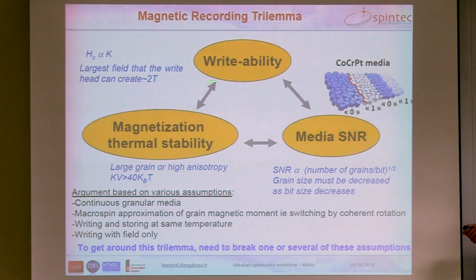But if we increase the anisotropy, now we have a problem of writability, because this electromagnet, the writer, which is a small electromagnet, can at most deliver a field of the order of 2 Tesla, and this is limited by the magnetization of the pole piece of this electromagnet. And nowadays we know with iron cobalt alloys, and with nitrogen in it also, to reach a maximum magnetization of the order of 2.4 Tesla, but the head can hardly produce more than 2 Tesla. And this field that we need to write is actually proportional to the anisotropy. So if we increase the anisotropy, we need to increase the write field, and somehow we are limited by the maximum field that the head can provide.